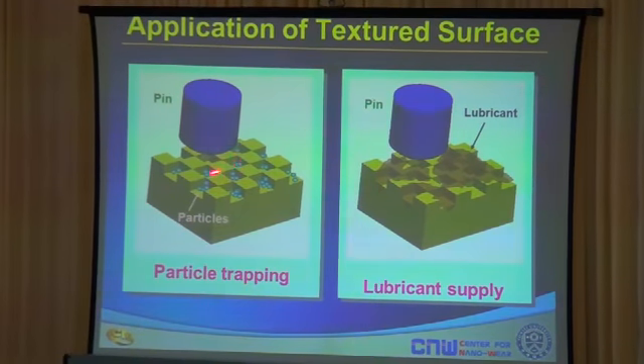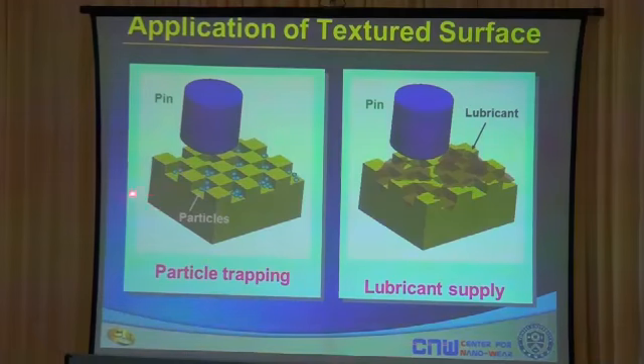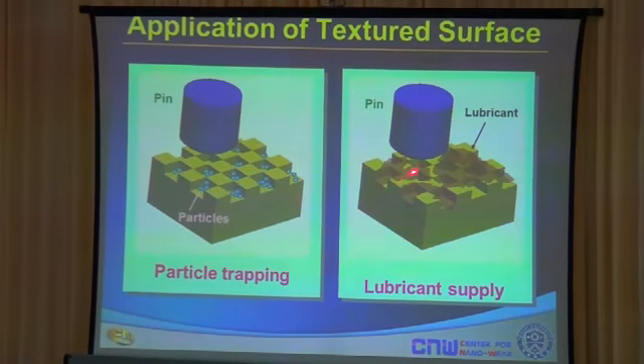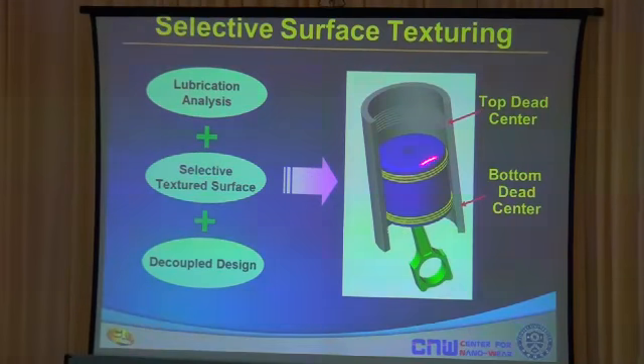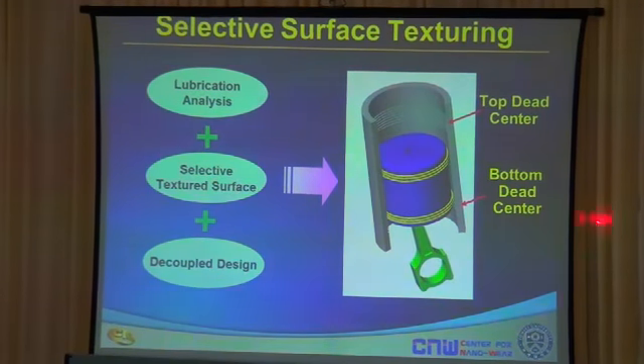So this is a conceptual idea about what texturing is. We would artificially fabricate these grooves on the surface that can act to trap the wear particles. And also in the case of lubricated systems, these traps are able to contain lubricant as reservoirs and supply it to the interface more readily. Now this kind of concept actually was proposed for cylinders and engines. And if you know about the lubrication state of engines, the piston ring travels between the top dead center and the bottom dead center.